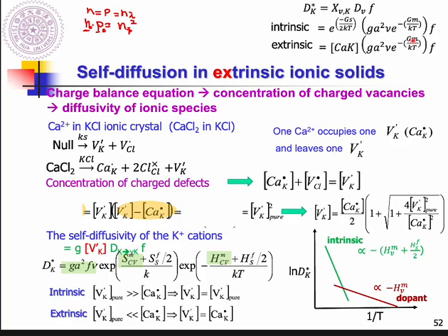So what does this result actually tell us? At lower temperature, it will probably be dopant control, like room temperature; in some cases it will be dopant control. But at higher temperature, 1 over T will be smaller, and it will be intrinsic control. So it goes from lower temperature, increasing to higher temperature. So depending on your targeting temperature,